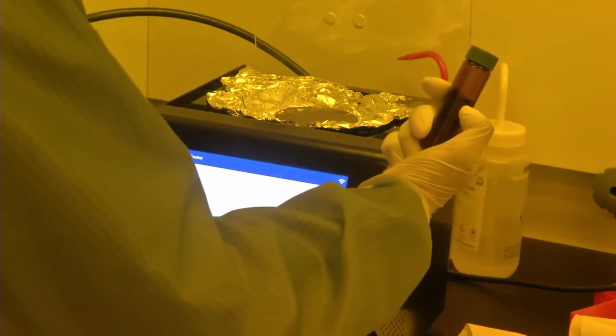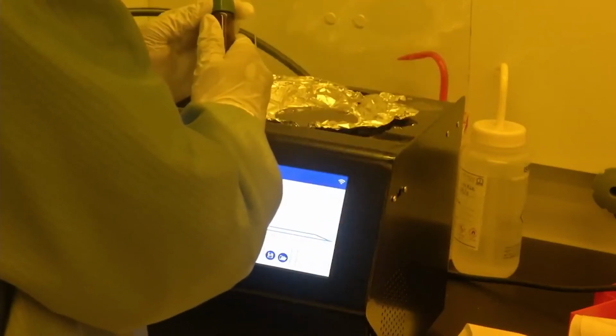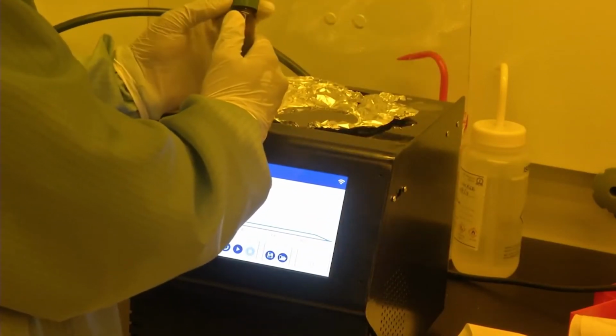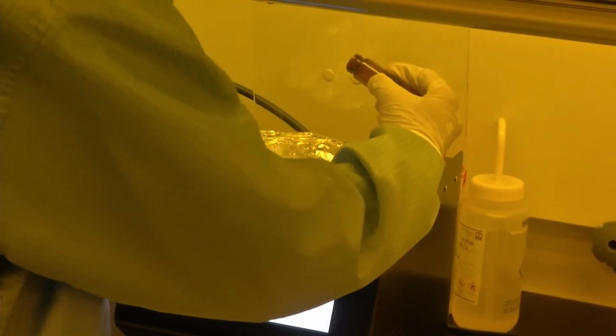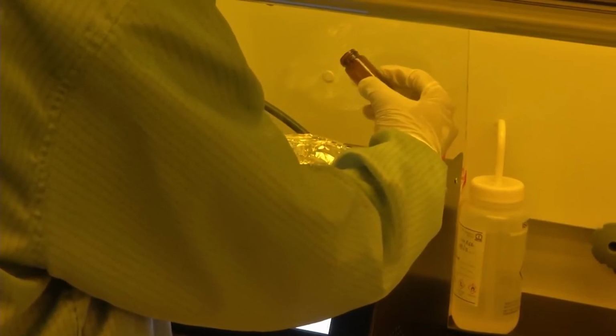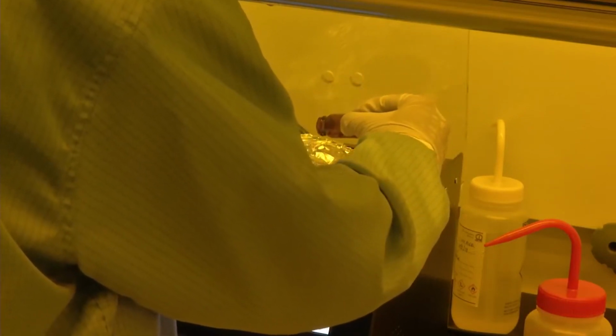So now my colleague will use a dedicated vial for pouring the precursor onto the silicon wafer. Pouring itself requires some amount of practice. We need to ensure that there is no bubble formation. So we need to be very careful while pouring the polymer precursor. We need to pour it very gradually to ensure that there are no air bubbles formed on the silicon wafer.